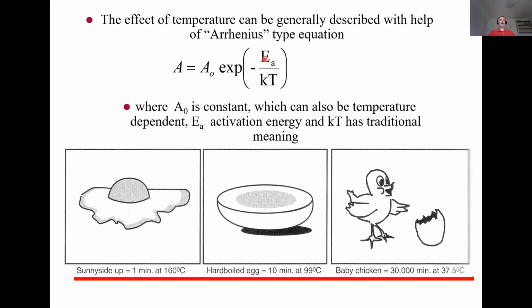So this basically comes back to the basic rule of thumb for a reliability engineer: if you can decrease the operational temperature by 10 or 20 degrees, then you can increase your lifetime or reliability by a factor of 2. That could be something else, but that is the basic idea. Being able to reduce the maximum operational temperature from 100 to 90, you end up having, instead of 20 years mean time to failure, 40 years mean time to failure, or your lifetime is going from 10 years up to 20 years. Definitely not always true exactly like that, but the direction is the same.